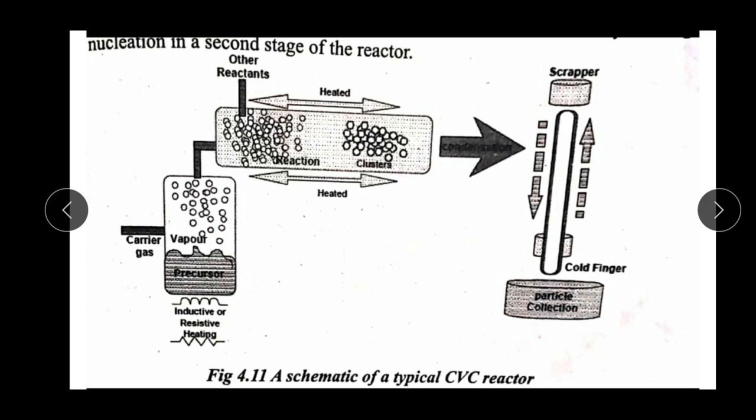Because CVC processing is continuous, the production capabilities are much larger, with quantities in excess of 20 grams per hour having been readily produced with a small scale industrial reactor. A further expansion can be envisaged by simply enlarging the diameter of the hot wall reactor and the mass flow through the reactor. Hope you understand the chemical vapor condensation process.